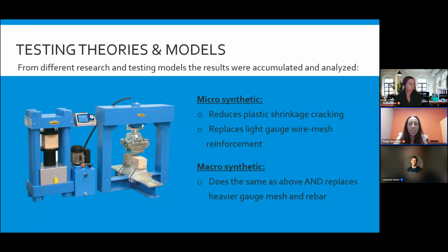And this is why we're able to look at this to have light cracking, or when we're looking at racking on a slab, moving fork truck traffic. It's just another way to design from looking at it from a post-crack perspective. And what we're able to get from this is the residual strength post-crack from the addition of fibers. And so essentially we're testing that residual strength and how we're able to get our numbers for this.